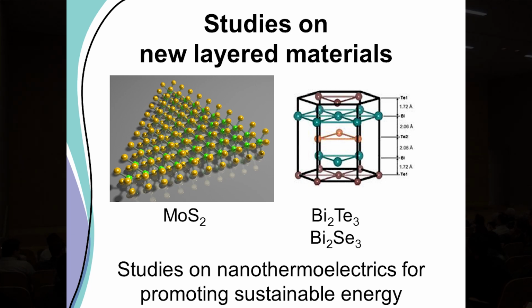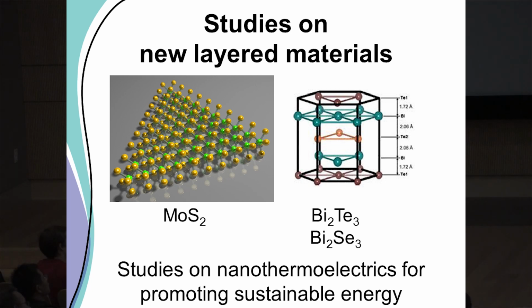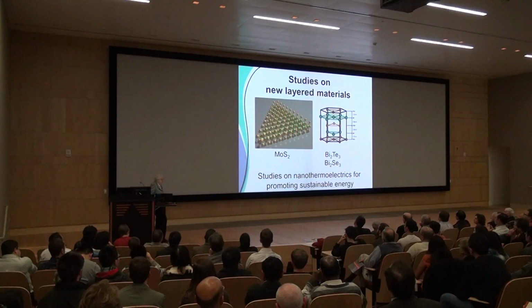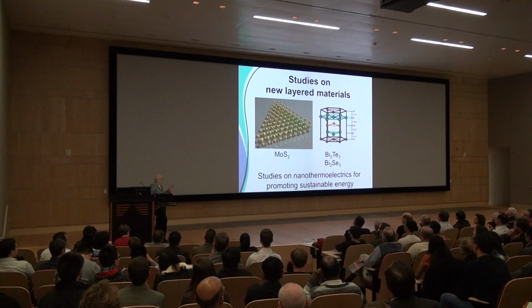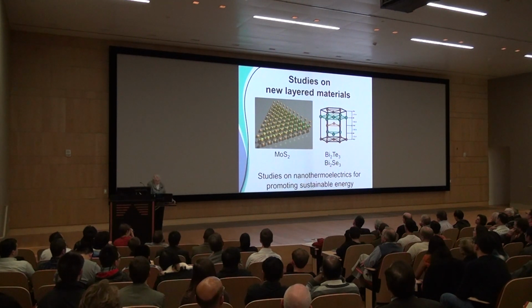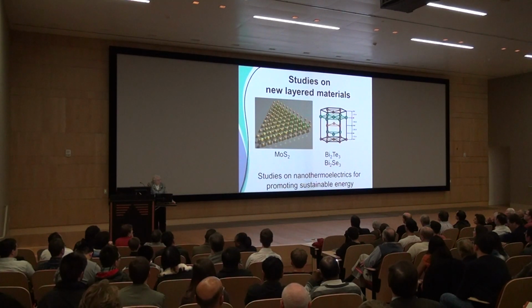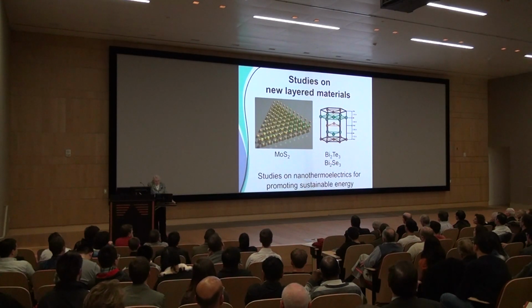And the other thing that we're working on are layered compounds. So MoS2 and bismuth telluride, these are layered compounds that are interesting in materials science for different things. So MoS2 is a big lubricant, a commercial lubricant, very popular for that. But it also, a single layer is fluorescent, so you get a spectrum from it. But when you have two layers, that doesn't happen, just one layer. So interesting things with it. Bismuth telluride is a thermoelectric topological insulator. It has different interesting current properties, but it's a layered compound.